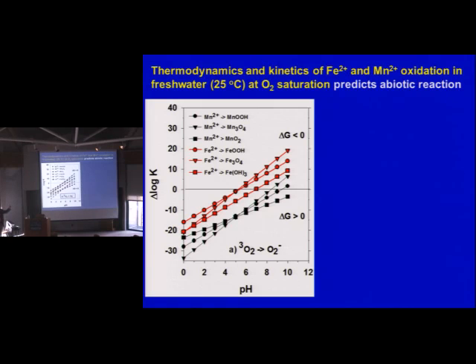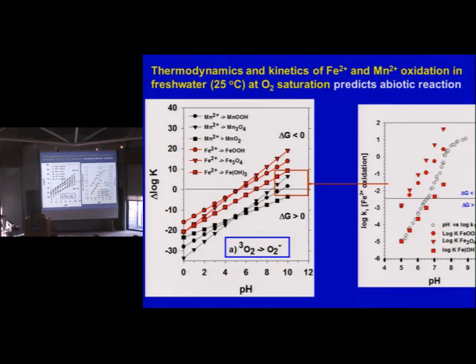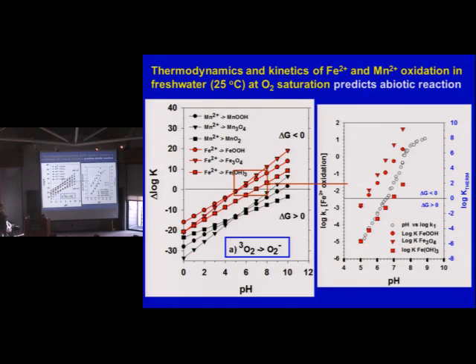And most chemical reactions will go by 1 electron transfer at a time or 2. Very rarely do you do 3. NO, nitric oxide, is one that could possibly do that. Now, if I blow up a section here, I have on this the oxidation rate in these circles versus the pH. So you notice that this is linear, just like the thermodynamics is linear. That means I have a linear free energy relationship between the kinetics and the thermodynamics. And as I tell my students, when you get one, cherish it, because what that means is you probably got something consistent with Marcus theory.